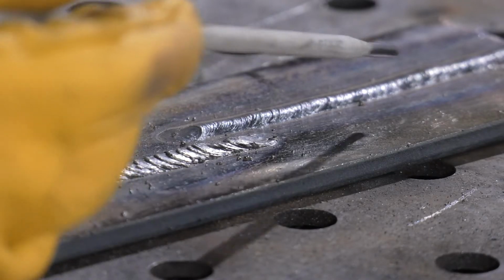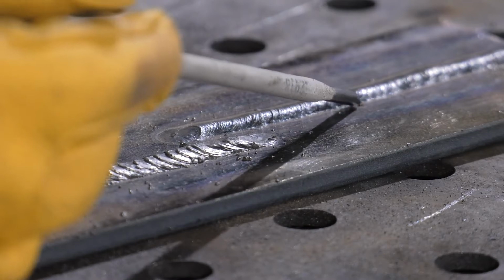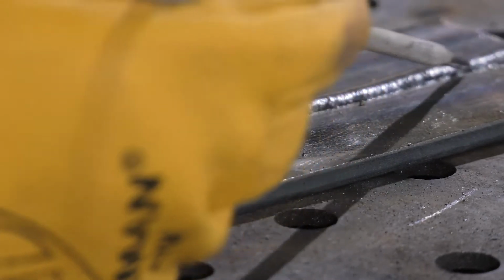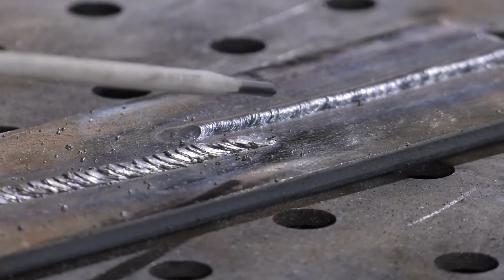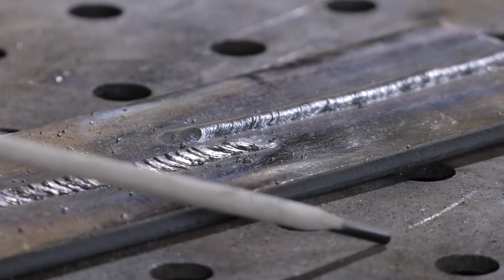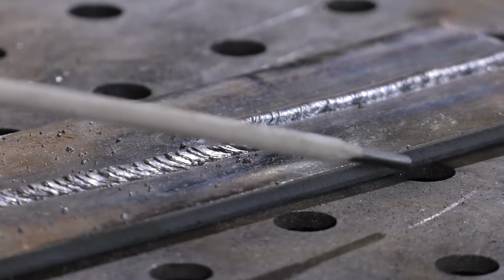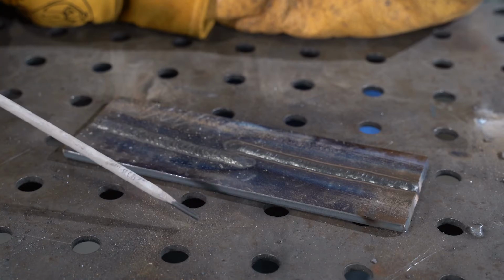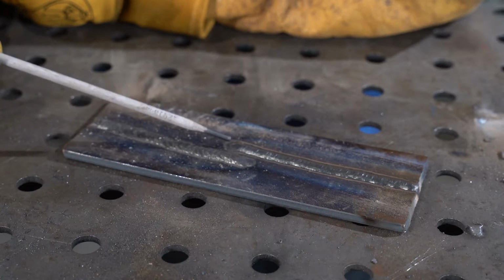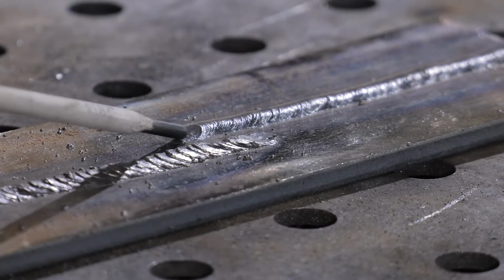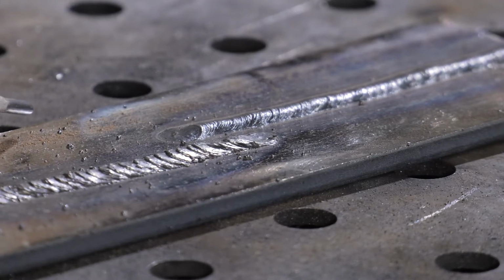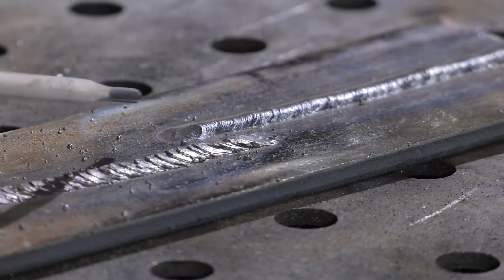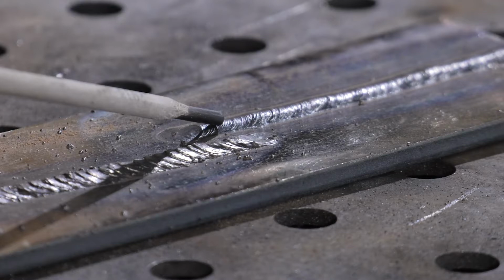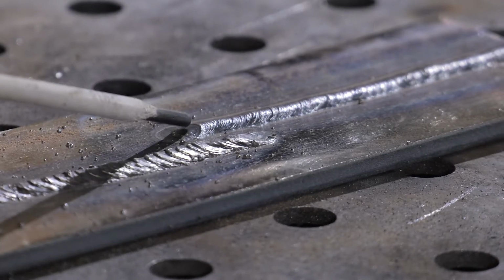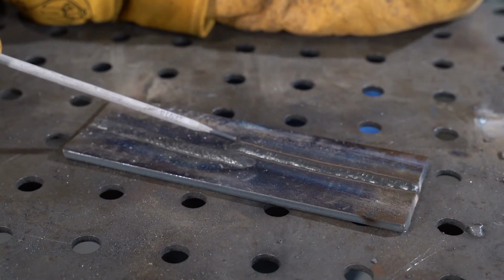You notice over here with the 7018, it's a little bit smoother. It's very clean along the edges. This is because we're just giving it a little bit of a drag motion, not really trying to manipulate the arc, again, because we do not want to have slag overlapping into the weld bead itself. So very common to keep a nice tight arc with the 7018 and try and limit any motion at all.